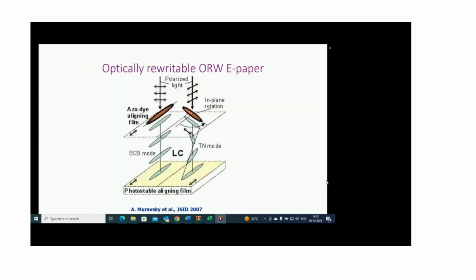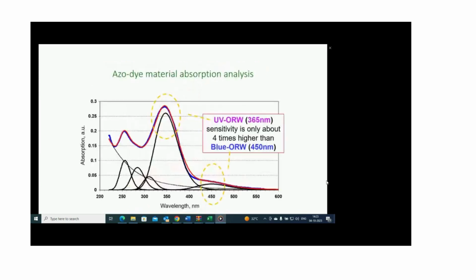So the idea of optically rewritable paper is very simple. You just rotate the molecules of the nanosize azo dye layer, and because of steric interactions, the molecules will rotate liquid crystals in the bulk. So in principle, you can change the twist angle of the liquid crystal. If you change the twist angle, you can change the direction of the polarization, and you can change the image, the gray level.